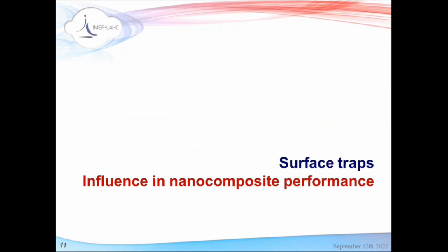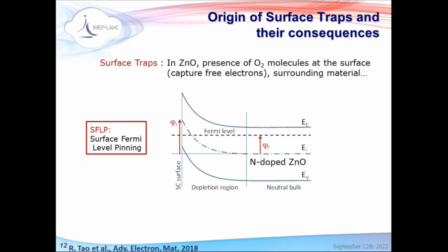So in our simulations, we included something that was missing before. It's surface traps. So we will see what this is. This is classical, typical in semiconductors. So it's present in all semiconductors at the surface of the semiconductor. So it's present in thin films, in nanowires, etc. So what is the origin of the surface traps? It's because the surface is not as good as the bulk.